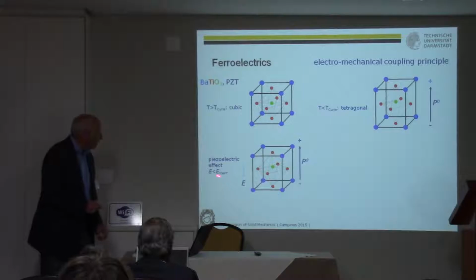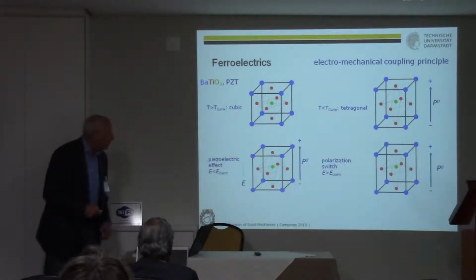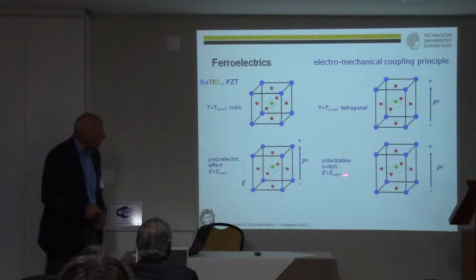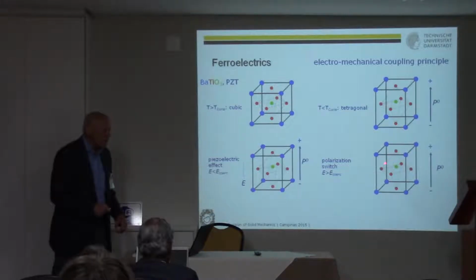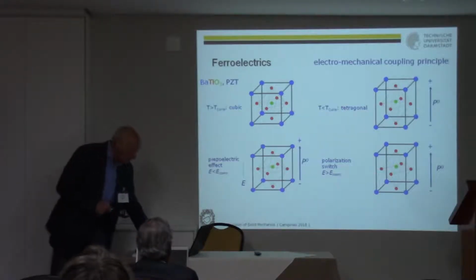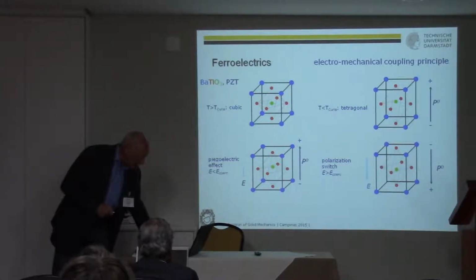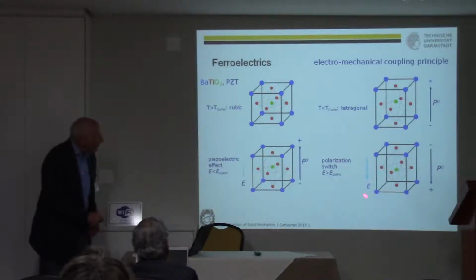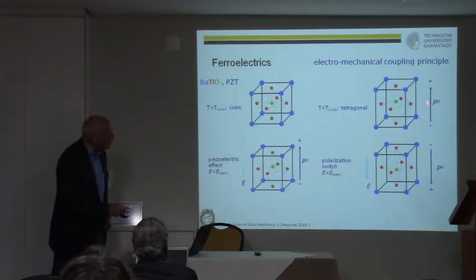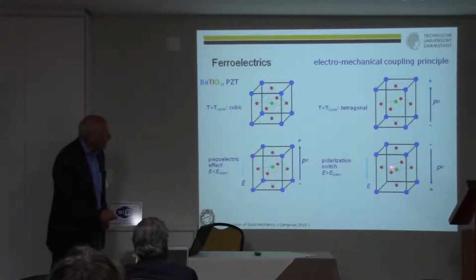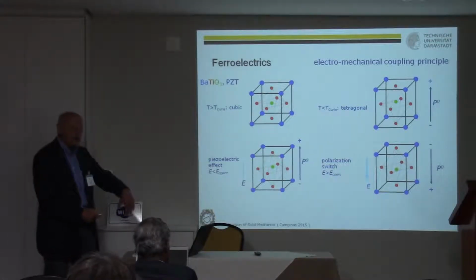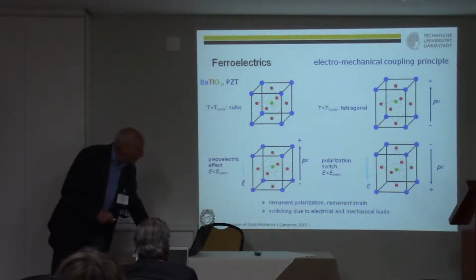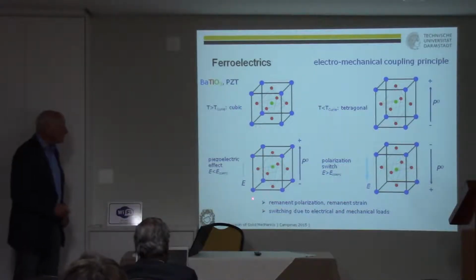But if the field is above the coercive electric field, then you get a switch in the position of this green oxygen atom here, and you see it switch. For instance, here, when the field is directed against the initial polarization, the atom switches and gives rise to a new direction of the polarization. That's clear? And this then gives rise to the remanent polarization, remanent strains.